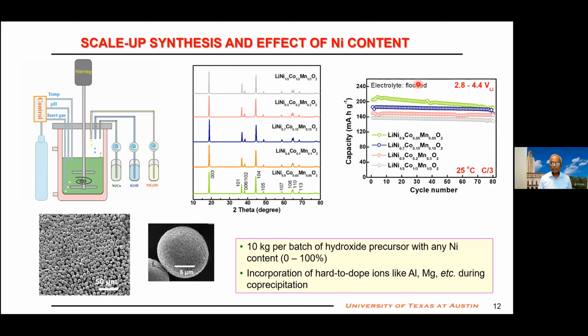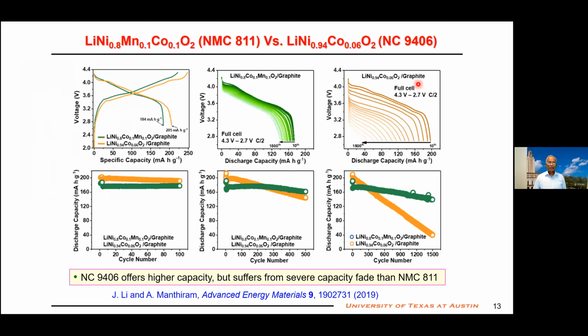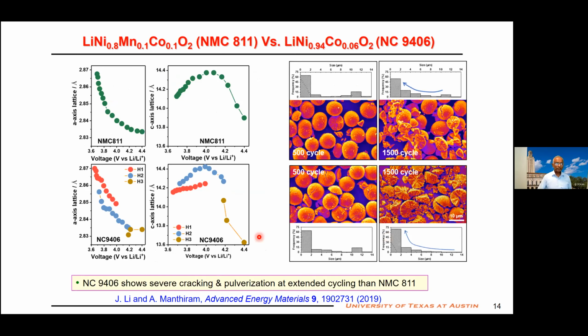This is, of course, with lithium metal to show you, but hereafter I'm going to show you all full cells with graphite anode. I'm comparing two materials here, one with 80% nickel, another one with 94% nickel. You see here, as soon as you go from 80 to 94, the capacity fades a lot. It's only a 14% increase in nickel, but a drastic influence on the cyclability. Why? When you go to higher nickel, you obviously extract more lithium. That means you have more phase transformations happening, volume change. So at 1500 cycles, if you look at it, the 94% material has more cracks than the other material.